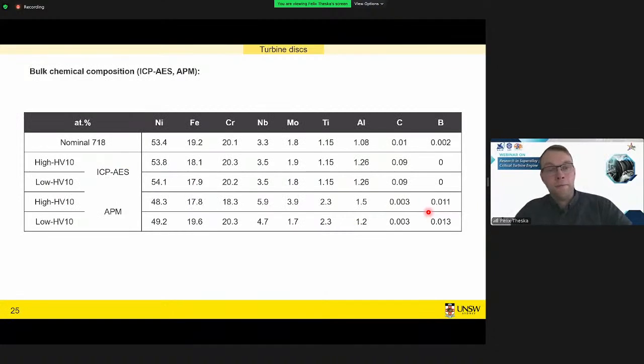Okay. The next step, we did some chemistry analysis. The top is the specification for this alloy. Then we have some inductively coupled plasma AES. On the bottom side, we see our atom probe results. With the AES results, there's nearly no difference between them. So there's no significant chemical segregation going on, although the atom probe shows some slight differences, but again, it's a very highly localized technique.